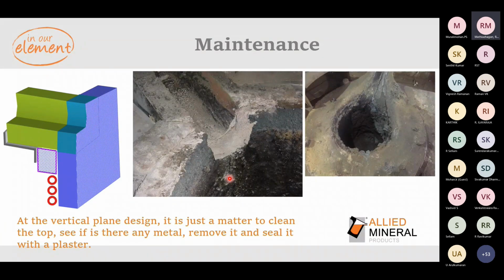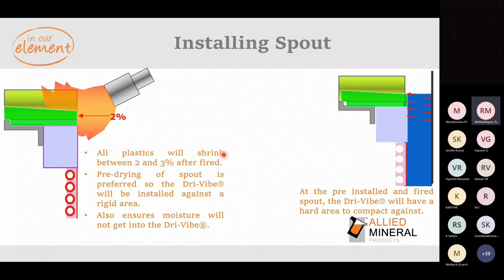So you can see when we do the spout first and the working lining second, the maintenance is very minimum. We always recommend plastic refractories for the spouts, which has 2% moisture. So prior to the working lining, we need to remove this moisture and allow the refractory to shrink. So we recommend to use an external burner, and depending upon the quantity of the refractory being used, the dry out of the spout timing can be scheduled between 2 to 4 hours.